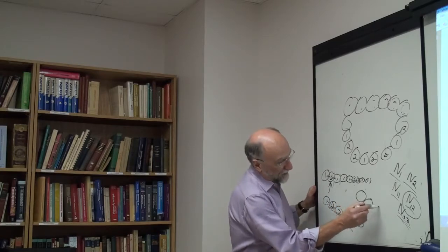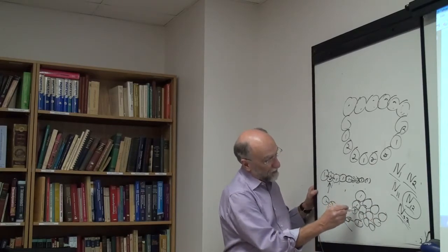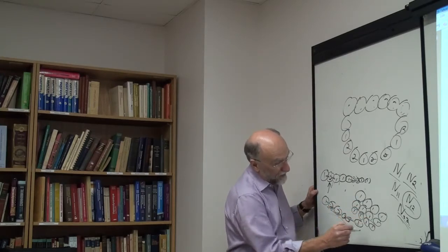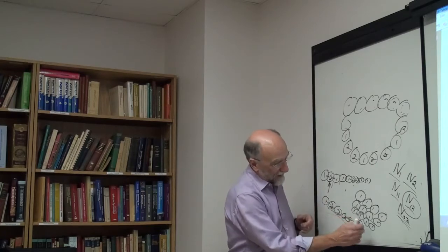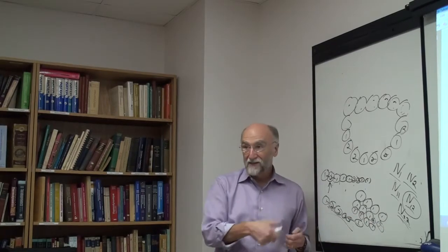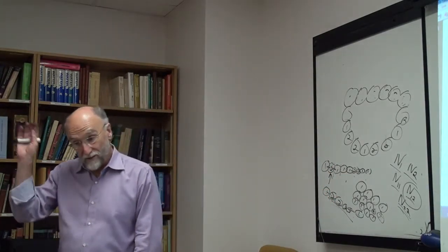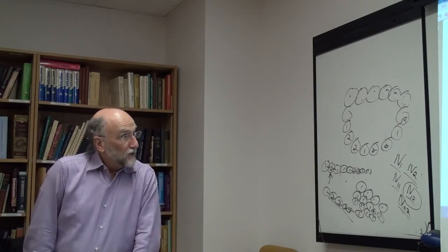But now let's try to do the same thing with a 2-dimensional lattice. First of all, I put all the 1s on the lattice sites. Now I try to shove in 2s in order to form the 1-2 bond, but you can't shove a 2 in here, because then this moves over, and you can't do it in 2 and 3 dimensions. You can't insert things so simply just by expanding your lattice, and the whole thing becomes extremely complicated the minute you go beyond 1 dimension. So the exact solution in 2 and 3 dimensions is beyond what we can do.